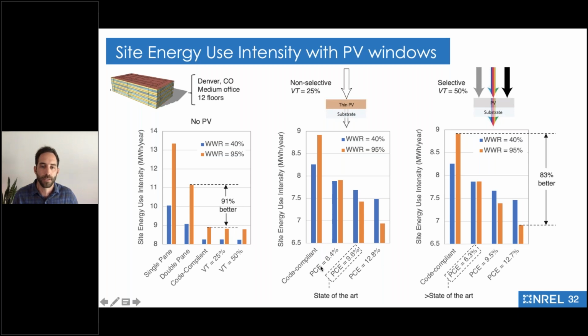And so even if you're at, say, 6% power conversion efficiency, you are definitely improving your site energy use intensity relative to code compliant. If you go up to a better power conversion efficiency, you're further reducing your site energy use intensity. And again, if you go to what is not theoretical maximum, but it's getting closer, 12.8% power conversion efficiency, you've dropped your site energy use intensity pretty significantly.